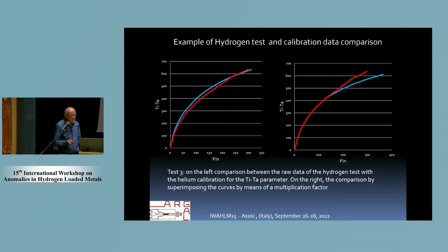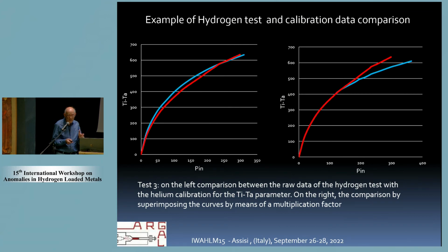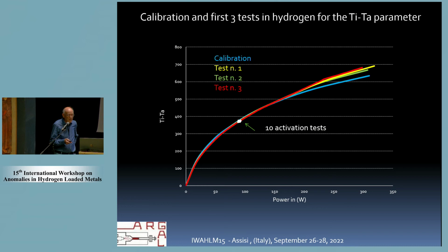You can see here two couples of graphs showing raw data comparison between the experiment and the calibration, and the same curves after the overlapping operation. You can see that at a certain point we have an inflection of the curve in hydrogen, meaning there was the initiation of extra heat production. The same effect was detected from the temperature of the reactor.